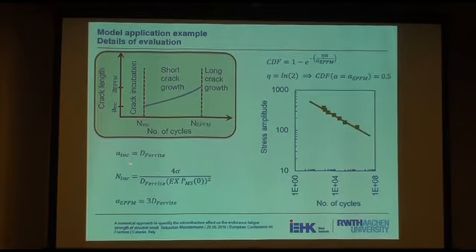We believe that the crack at the end of the incubation phase will have a length which is more or less the diameter of the ferritic phase. There's a certain number of cycles in the incubation phase which mainly depends on the fatigue indicator parameter in the vicinity of the inclusions. And we also believe that once the short crack has reached 3 times the ferritic grain diameter, it should become a long crack, at least with a probability of 50%. So here we could also calibrate this cumulative distribution function law.